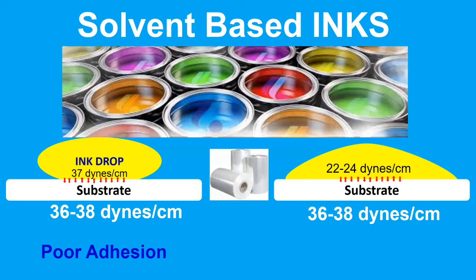inks, solvent-based inks. For example, if the surface tension of the solvent-based ink is 37 dynes per centimeter, and the surface energy of the substrate is 36 to 38 dynes per centimeter, it means we will not have perfect adhesion. Our adhesion will go very weak, and printing inks will peel off from the substrates.